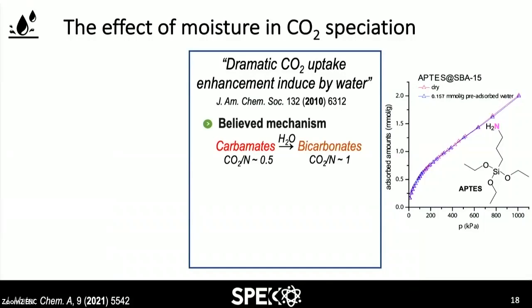If you look at the adsorption isotherm, you can see that there is no significant change between the adsorption capacity under dry or moist conditions. However, there were some debates in the literature saying that probably there should be an increase in CO2 uptake induced by water. So once the material is exposed to water, it absorbs much more CO2. And that mechanism was believed to be based on the formation of a bicarbonate. If you look at the stoichiometry, here is 0.5 and here it's 1.